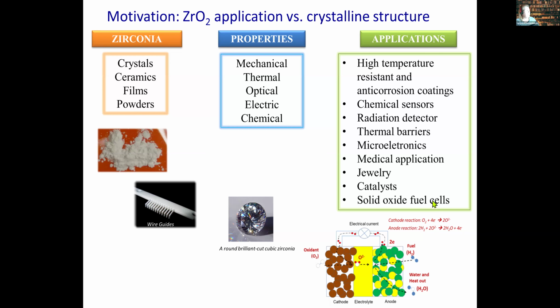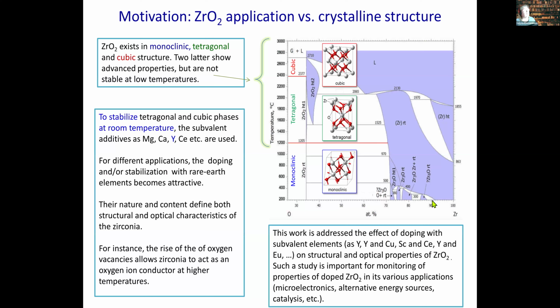And in all these applications, the most important question is the effect of the crystalline structure, and how the crystalline structure will govern the future application. Usually, zirconium oxide appears in the monoclinic crystalline phase. To get the tetragonal or cubic phase, we can go to very high temperatures to have this crystal transformation, but upon cooling we get back the monoclinic phase. Stabilized tetragonal and cubic phases have much more advanced properties than the monoclinic one: high dielectric constant, high ionic conductivity, and more stability against corrosion.